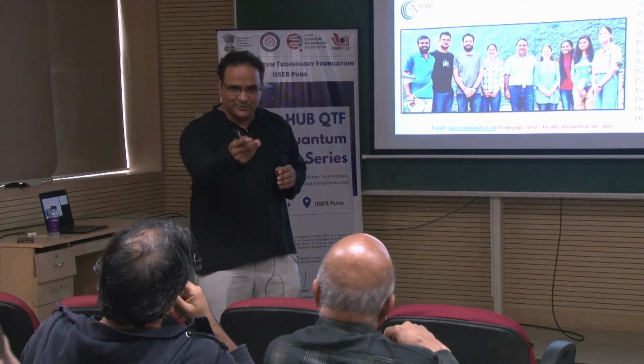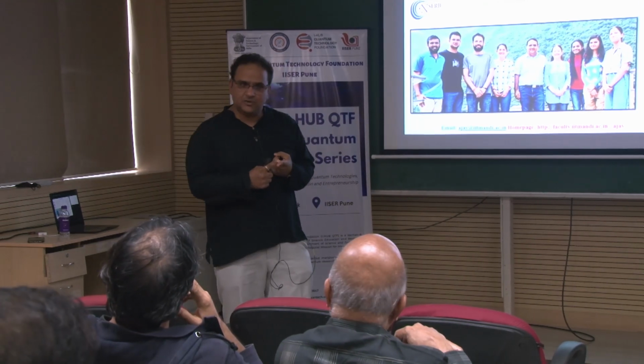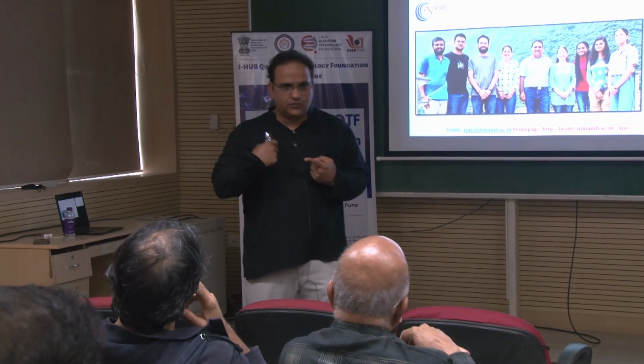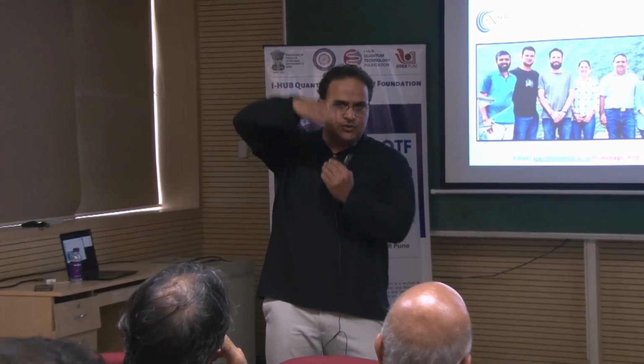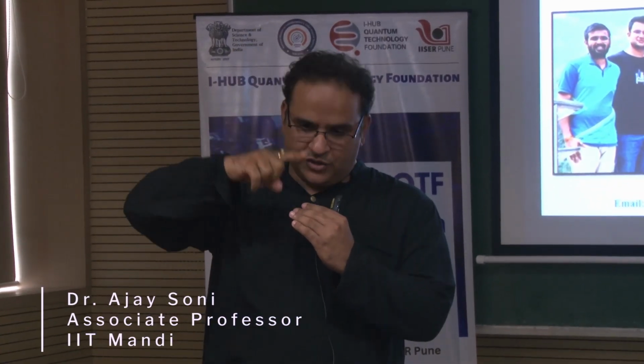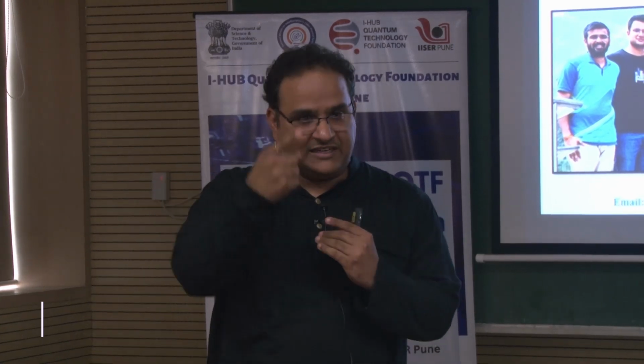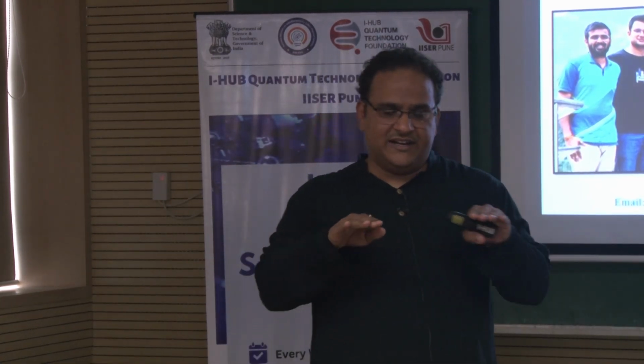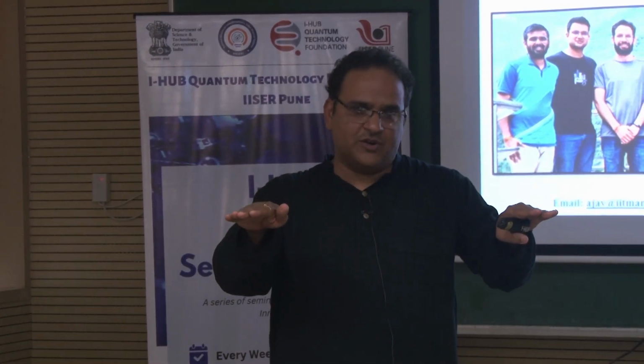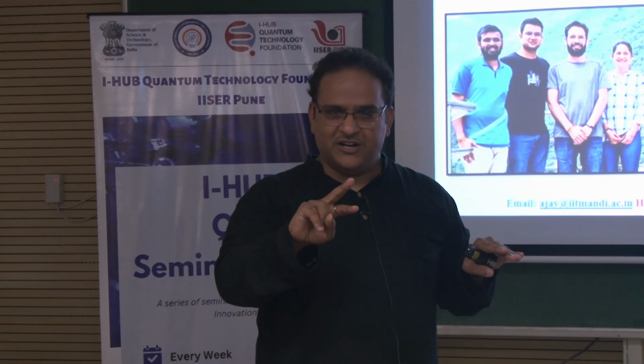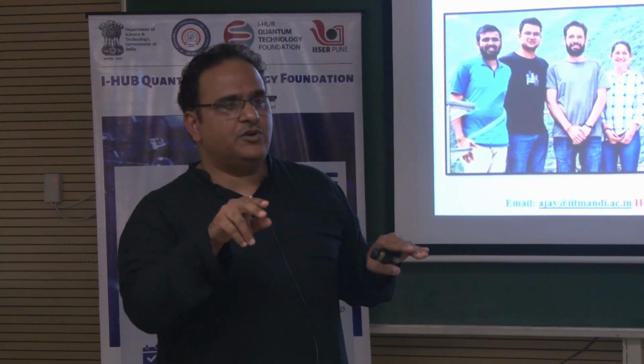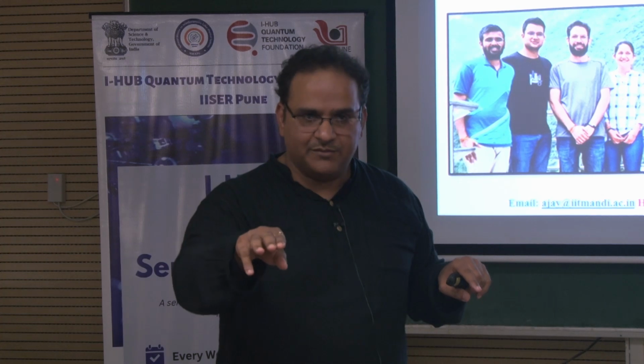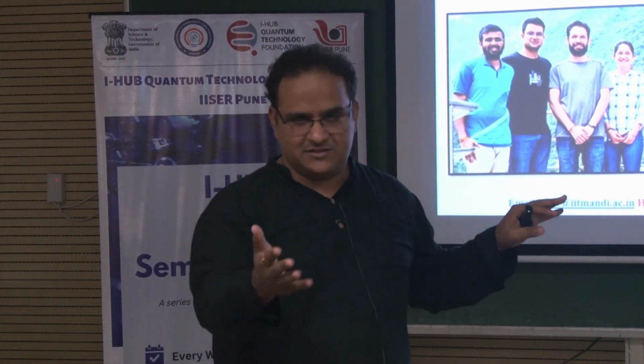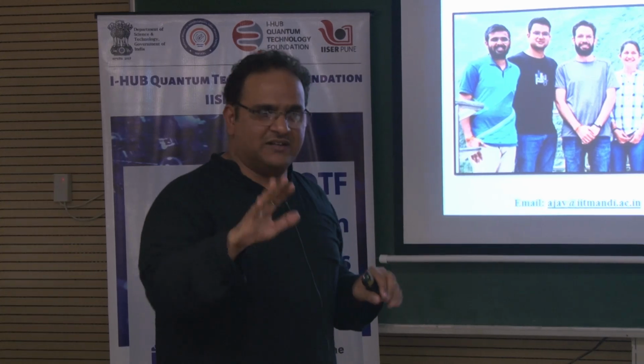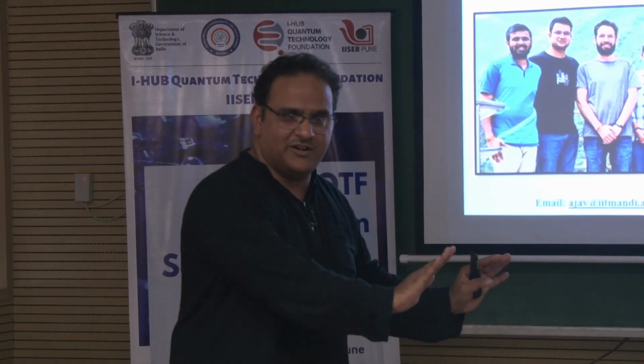So let me come back to all three points. Number one was what is happening below 16 nanometer. So one of the reasons which I feel personally is that because I am reducing the weight on the thin flakes, 16, 10, the restoring force of the vibrations is decreasing. At the same time, whatever phonons I am talking about are confined in two dimensions. So there are two factors. The E2g mode mostly tells about the phonon lifetime as well. If it is increasing, that means there is a confinement effect. But I am not sure at this moment whether this argument will really hold.